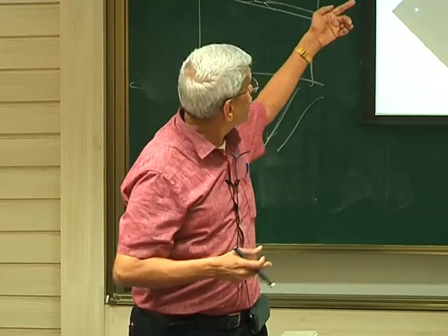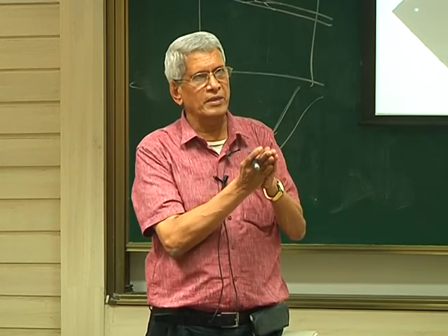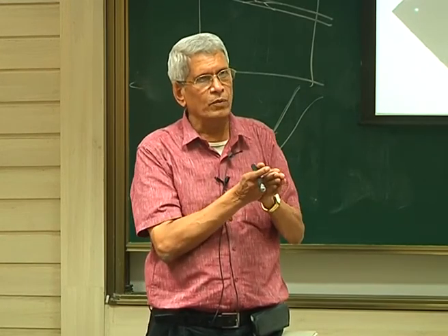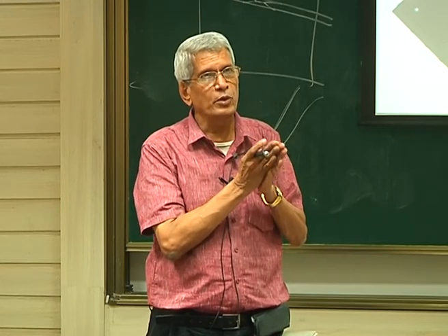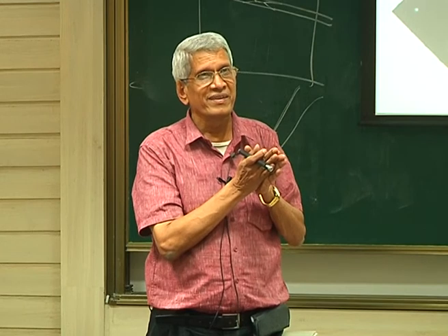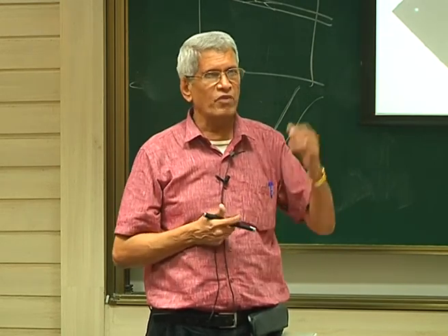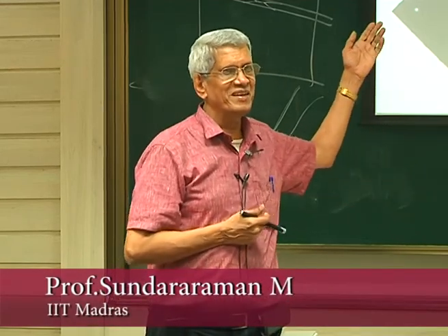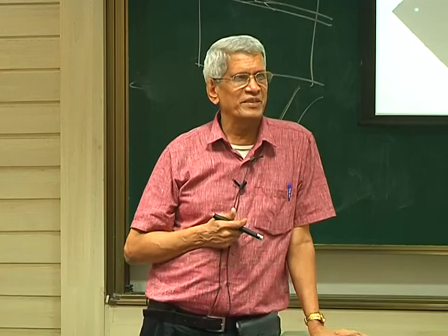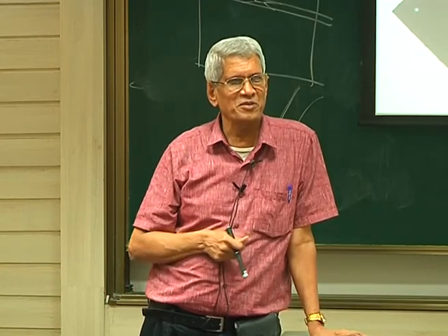If overlap fringes are there, then if you try to tilt this and make the planes parallel, you can very clearly see that from that pattern you will be able to get a twin pattern. Micro twins will give rise to a diffraction pattern similar to twins. From that we can say that though we see some fringes, this is essentially a micro twin which we are seeing. This sort of analysis has to be done.